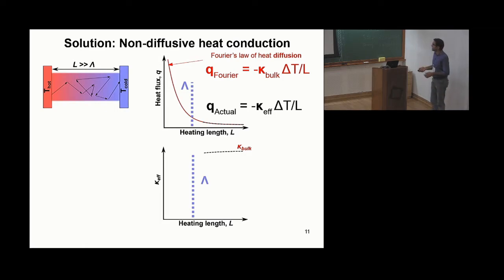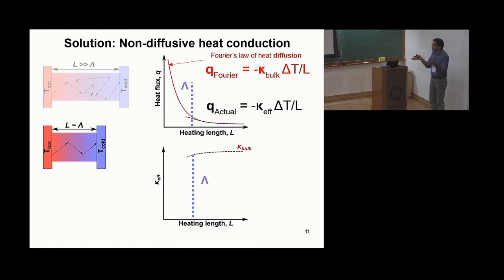Now imagine what happens when I try to bring the hot and cold end closer together such that the length scale is now comparable to the mean free path. You can see that the number of collisions are becoming fewer, so the transport is deviating from a diffusion process. What happens is the heat current that you measure is actually lower than what Fourier's law predicts.